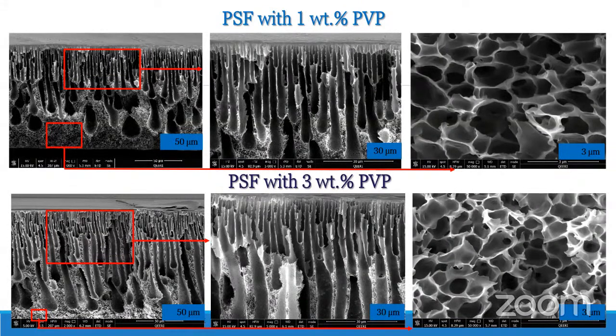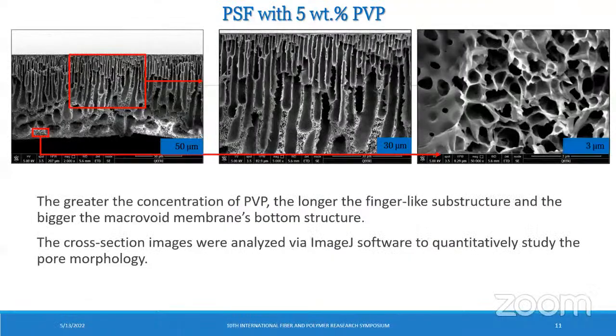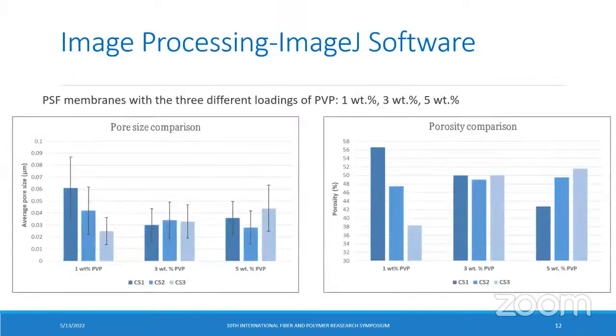Now, we came to the conclusion that the greater the concentration of PVP, the longer the finger-like substructure, and the bigger the macrovoid in the membrane's bottom structure. These cross-section images were also analyzed using ImageJ software to quantitatively study the pore morphology. And we have found that all reported data are within standard deviation.